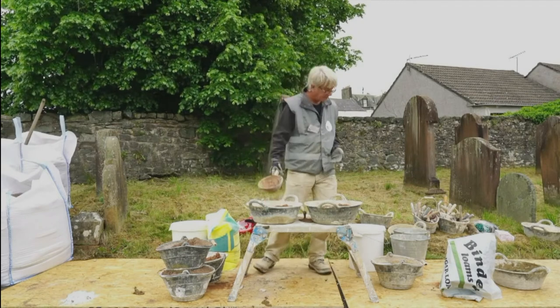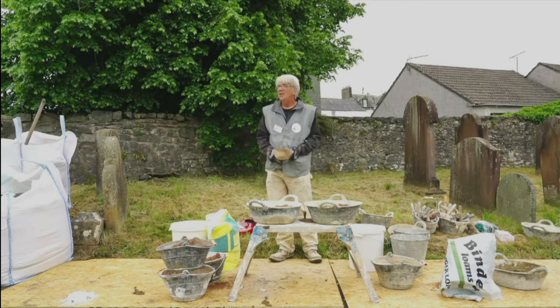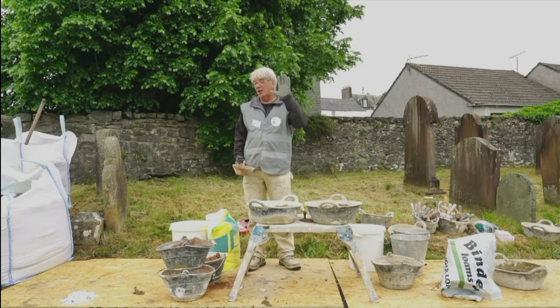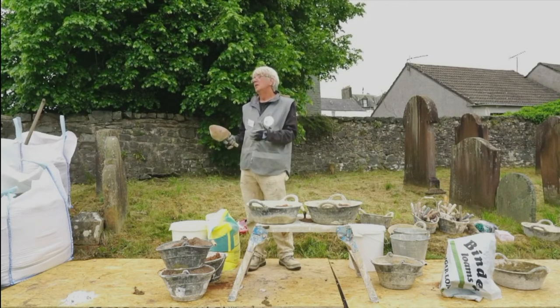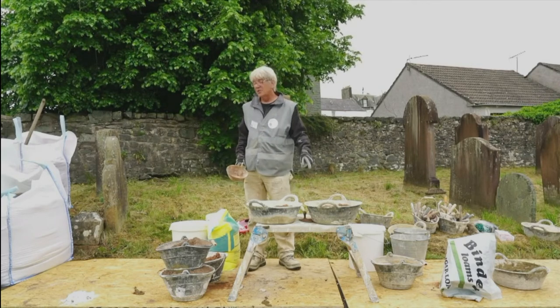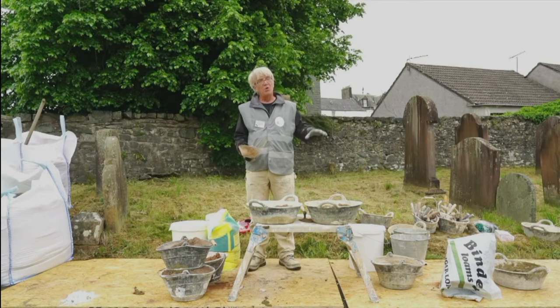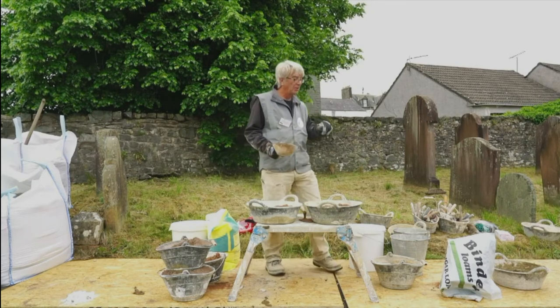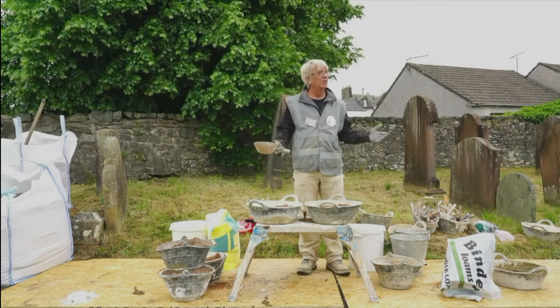So, okay. That was going to be the question, because I was thinking the average builder, or us, we're going to have to use commercially burnt lime, unless we build our own. Oh no, we are, and I do most of the time. Don't get me wrong, in the long term I hope that we will re-establish small-scale lime burning in every region, because there's no question it's more authentic, and it's actually a nicer material than this. This shrinks more. There's no question that the main consequence of higher firing is more initial shrinkage compared to if you burn it traditionally. That's unquestionably the case. So that would be an incentive to try burning it again at a proper temperature.